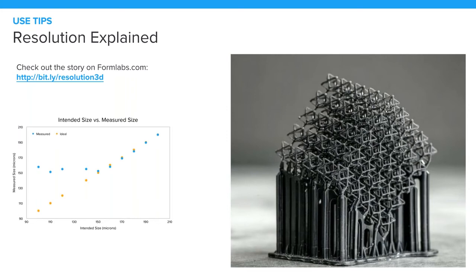As you can see in the graph here, the measured versus intended, so the measured is blue, and the ideal, which is the CAD model, is orange. They don't intersect until about 150 microns, which is our minimum feature size. The way we tested this, there's actually a great blog post. You can follow the bit.ly link on the slide. We had a block of material that had lines cut into it at different intervals, and each line was slightly bigger than the rest. If you have a line that's 0.15 millimeters across, it will print. If it's less, it's not going to come out quite as well.